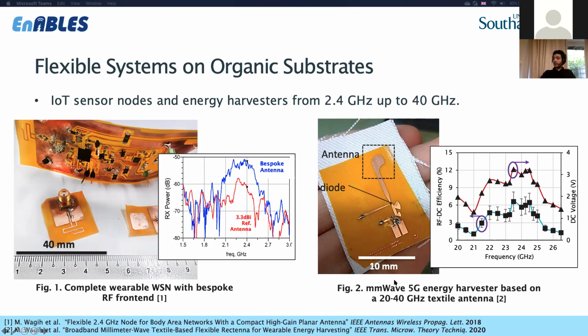We have demonstrated the first textile-based millimeter wave 5G energy harvester, which can convert very high frequencies up to 26 gigahertz into DC voltage successfully for energy harvesting applications. And the secret is we only have one tiny die standard semiconductor in the system, but everything else is distributed and based on our high resolution, highly reliable fabrication technique.